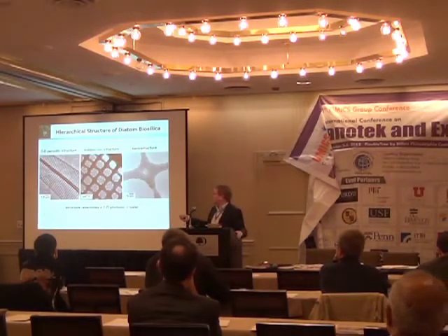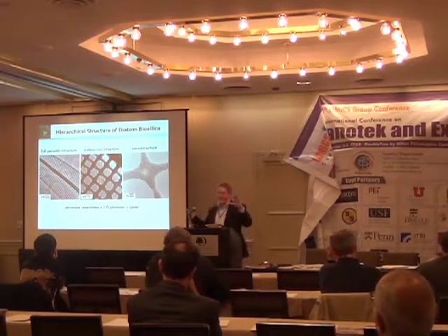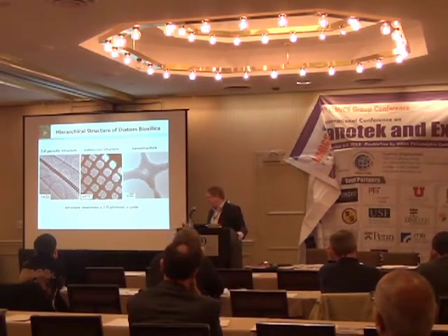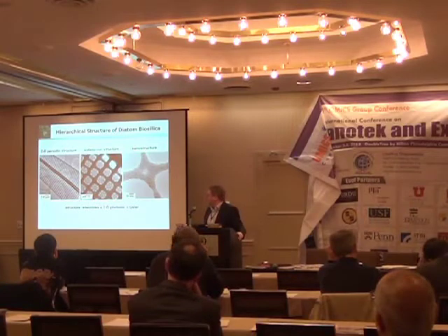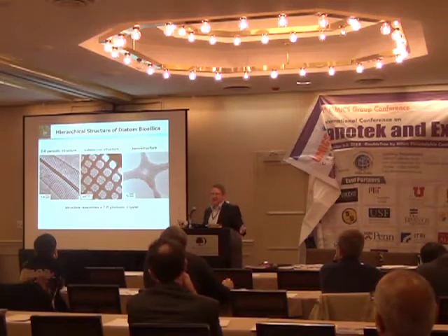If you look at the structure at increasingly higher magnifications, you see at the submicron scale this very ordered lattice that resembles a photonic crystal array. And embedded within this submicron core array is a series of fine structures and even finer nanostructures, with features below 10 nanometers.